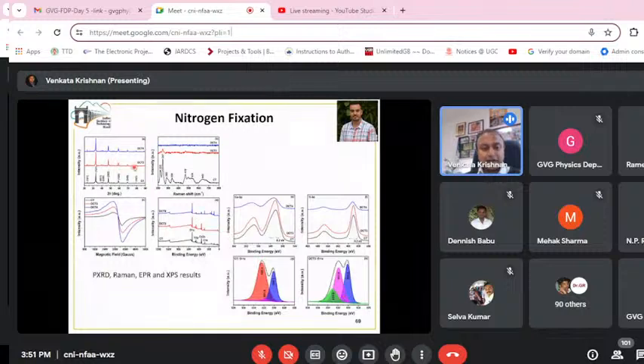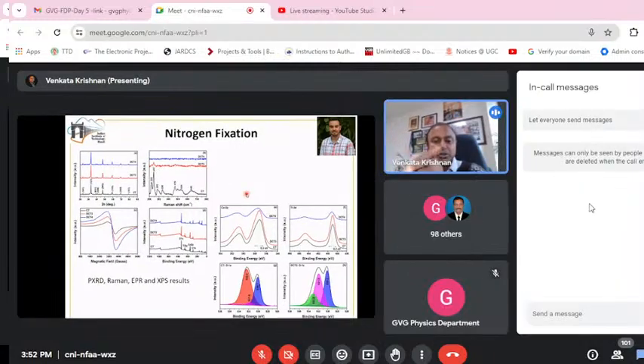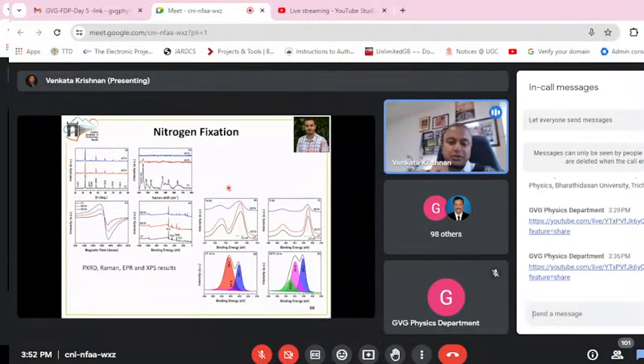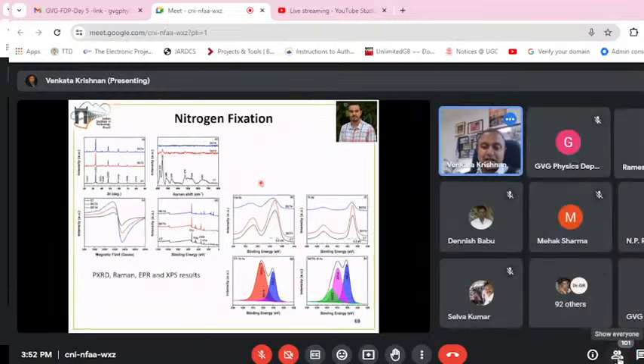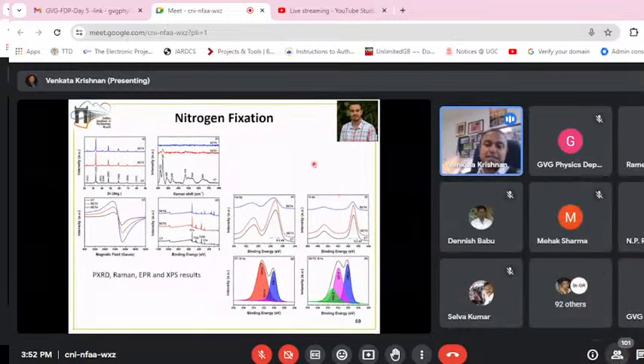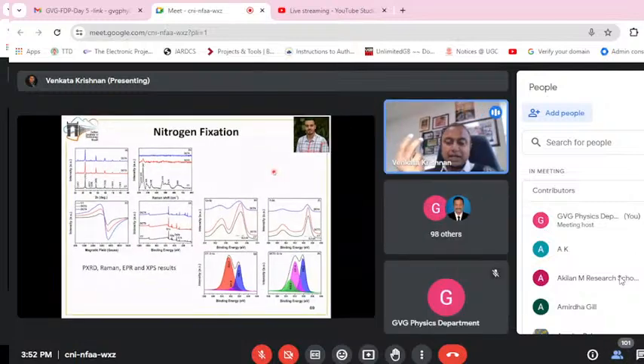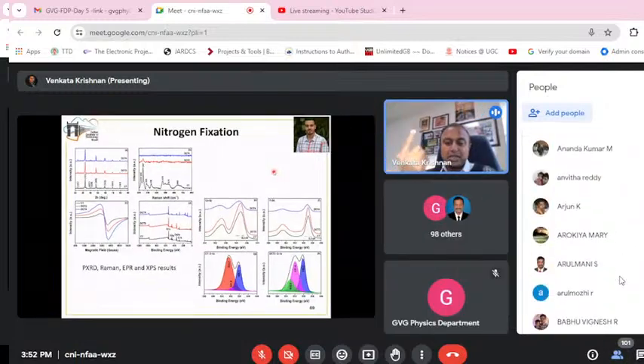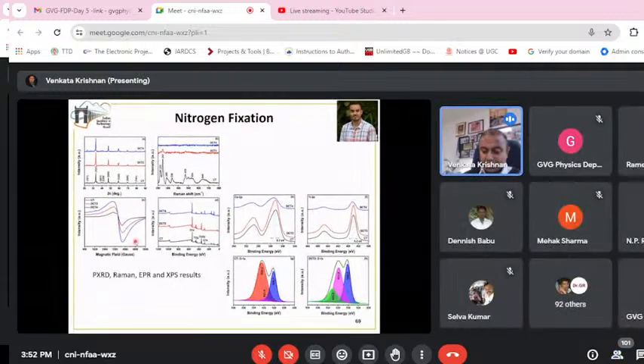Then we did other detailed characterization using XRD, Raman, and XPS analysis. From all the analysis, we were able to successfully prove the synthesis of the catalyst, and also observe the oxygen vacancies by some of these techniques, especially XPS, because it indicates that titanium in calcium titanate exhibits not only the +4 oxidation state but also the +3 oxidation state because of the oxygen vacancies present. We also did EPR analysis in order to understand the vacancy formation.